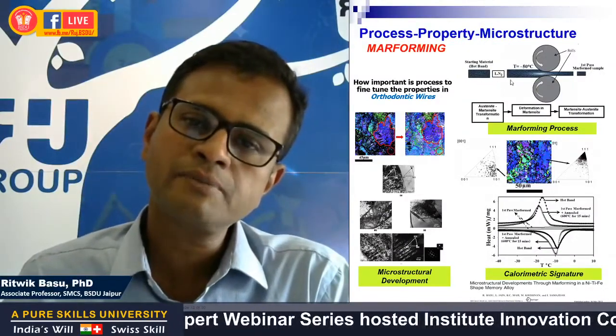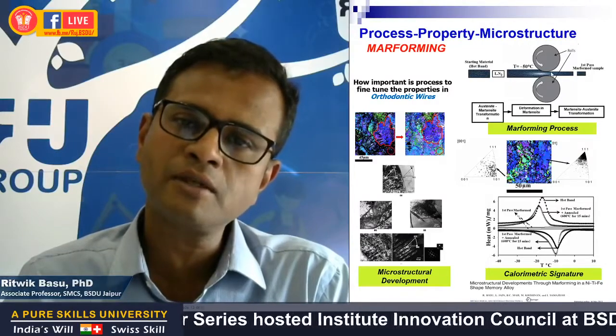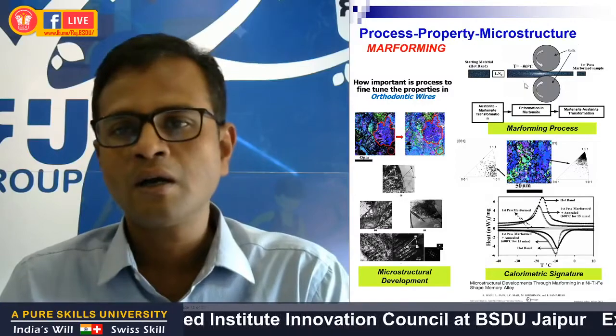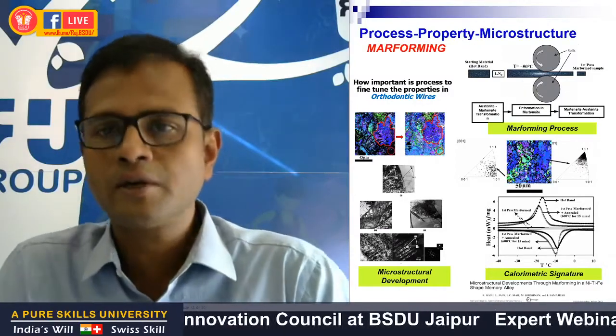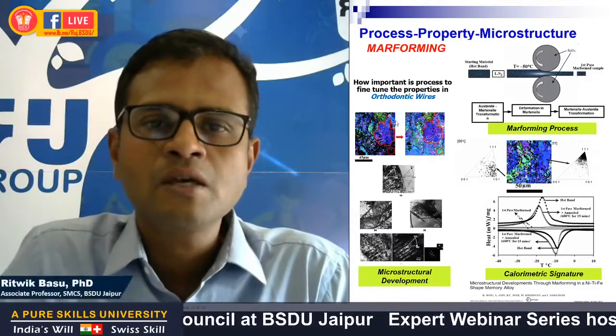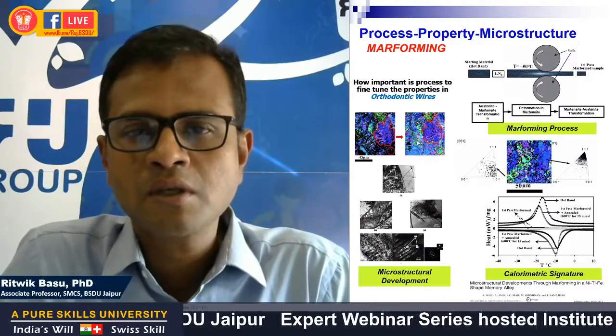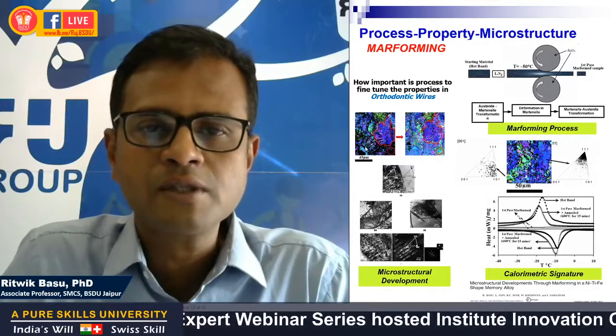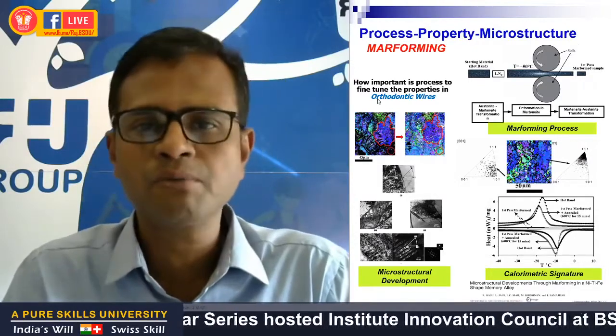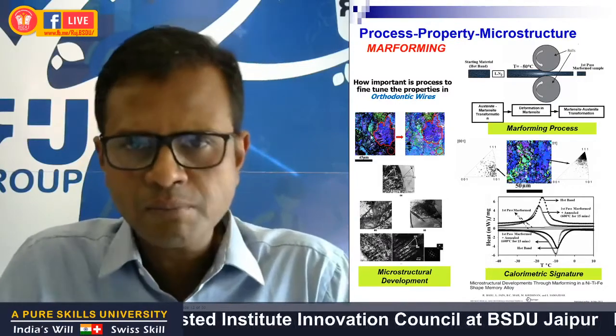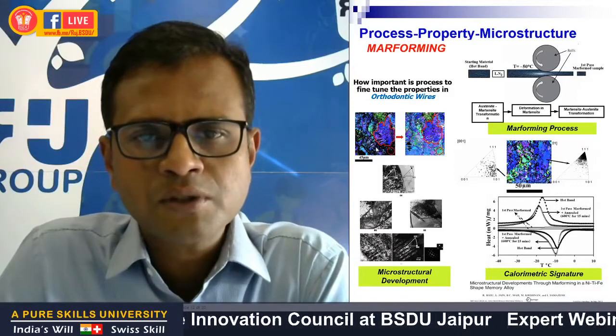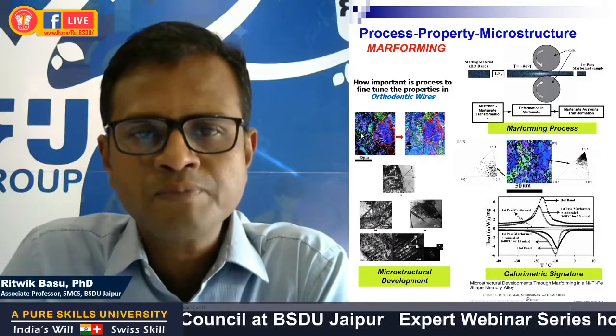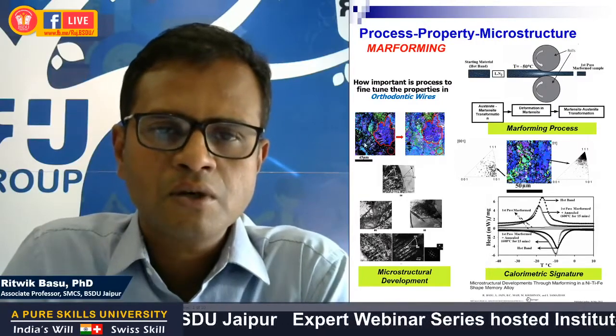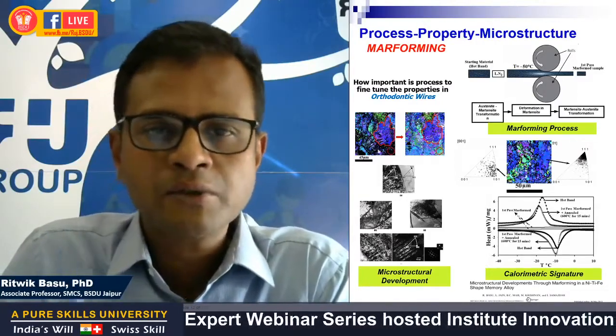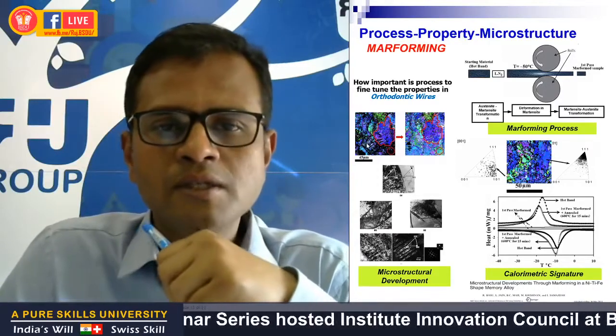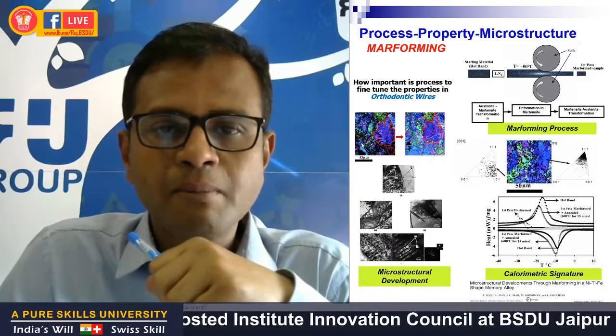So we tried to simulate the processing of these materials through a lab scale deformation process called marforming. So this is typically carried out in liquid nitrogen atmosphere. It's a very sophisticated process. So the post-marformed and the post-annealed microstructure brings out significant differences. The same region has been seen under microscope before and after annealing. So what we could see in the post-marformed or the post-deformed microstructure, there's a significant strain heterogeneity that is seen through dense dislocation blocks or walls. That means a higher dislocation density, which could not be indexed for EBSD, and that is the reason why some of these regions appear black.